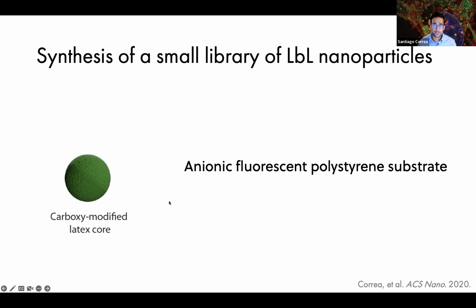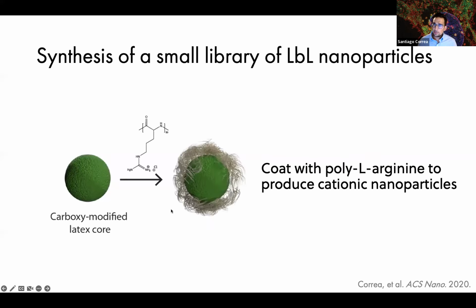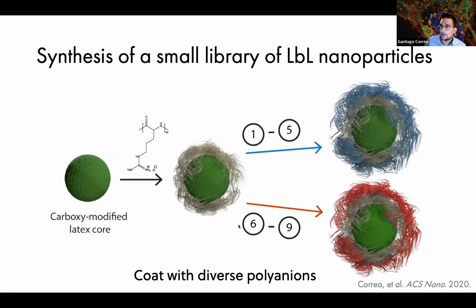So this is our core substrate, if you remember the anatomy from before. We coated these nanoparticles with a cationic polypeptide, polyarginine, to produce a cationic nanoparticle that would then be compatible with a number of different polyanions. The reason that we're restricting our library here to negatively charged surfaces is that there's a wealth of literature to indicate that cationic nanoparticles in general are fairly toxic. And so we wanted to limit our library to materials that we would expect to be likely to be biocompatible.